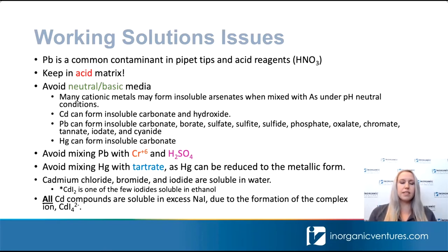Another thing to avoid is mixing lead with chrome 6. But if you're under acidic conditions, chrome 6 is going to be converted to chrome 3, and you shouldn't have issues as long as you're keeping that acidic. You also want to avoid mixing lead with sulfuric acid to avoid the insoluble sulfate formation. Same with barium and calcium. So if you're looking for a sulfur source that's not going to form the sulfates, we recommend using methane sulfonic acid. This is our main sulfur source we use for acidic sulfur standards.